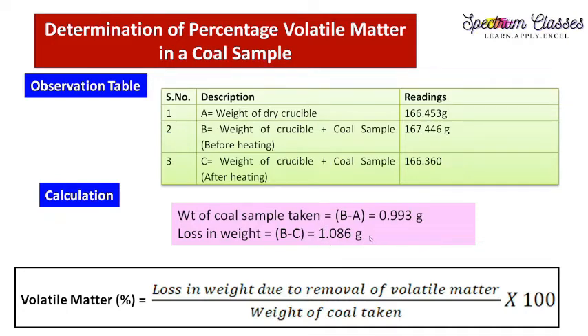I must tell you this is because the crucible itself also contains moisture. When we kept the crucible at 700 degrees centigrade, it loses some moisture, and this weight loss is because of that. I suggest you take the readings after the experiment from the same crucible used with the sample — weigh that crucible again and take the value from there, not from a crucible that was not heated before doing the experiment.